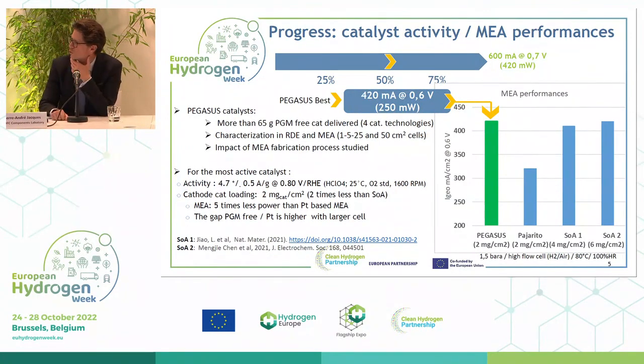We also measured that performance in conditions that are representative of the operating conditions that you can find in a stack. It was 1.5 bar absolute, under hydrogen and air, and at 80 degrees and 100% relative humidity. We also put a conventional MEA in that high flow cell, and we were able to measure that our materials are 5 to 10 times less active than conventional MEAs. Very important, because with this kind of cells you can reach very, very high values with conventional MEAs.